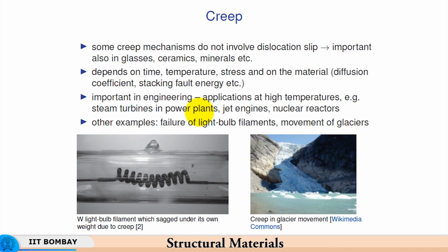pressure acting on the turbine blade, the temperature is an excellent recipe for the turbine blades to change their size and shape. Beyond the limit, the turbine blade will become completely inefficient in converting the energy in the high pressure gas into power. So, essentially the blades have to be changed because of the change in the blade angles or blade geometry as a result of creep. And creep is inevitable when material is exposed to high temperature and pressure for a duration of time. Jet engines, nuclear reactors.